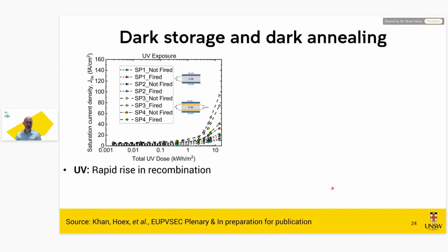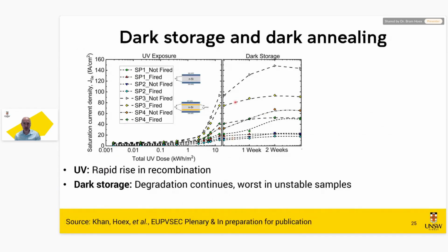If we then look at what is happening with this recombination current in the various stages, and we come to dark annealing or dark storage later. So we see that on the UV exposure, we see the recombination current ramping up. But then in dark storage, we see that this doesn't stop. So this is fully consistent with the results reported on solar cells and modules, where dark storage results in a further reduction of the performance, so an increase in recombination, decrease in VOC.